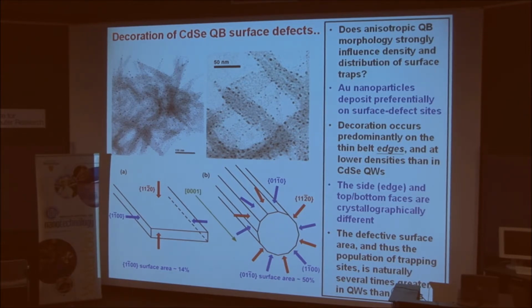I should have said that one has to make the assumption that the trap site defects are in proportion to the defect sites that can be decorated by these gold particles. Well, we identified the crystallographic facets on the edges of these belts, and they're in a different family of faces than the top and bottom surfaces. So it could be just that these crystallographic faces, which I've labeled in blue, are naturally more highly defective than the ones labeled in red. And so that's part of the explanation for the wire.